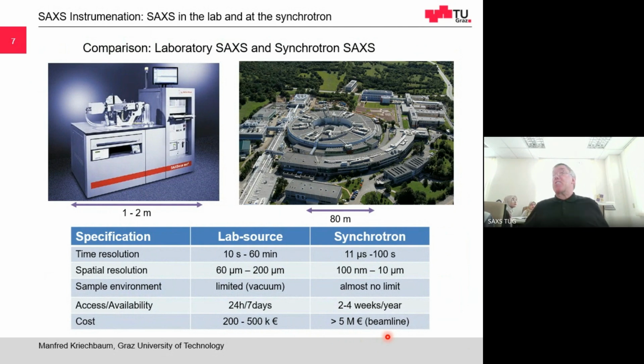For doing a SAXS experiment, you also need an X-ray source. And there are two sources available, either in a laboratory or at a synchrotron. A laboratory source you can buy for maybe $500,000, or you can build a beamline at an accelerator, an electron or positron accelerator. That is much more expensive, of course, but you also have some advantages. In the lab source, your exposure time is in the minute range. And with a synchrotron, you can make your diffraction pattern already in microseconds, because the intensity is 1,000 times higher than in the lab source.